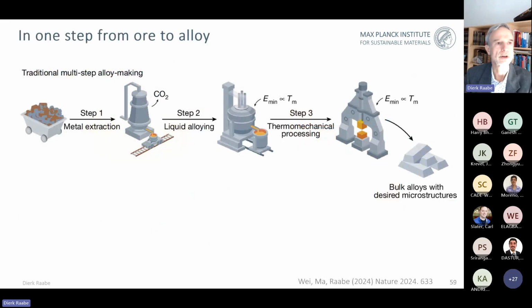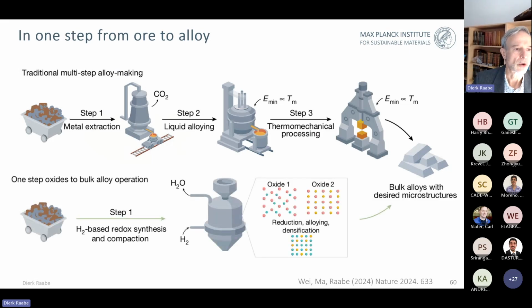And the last example I want to share is what we call one-step metallurgy, from ore or from oxides to alloy. That goes back to our textbook understanding that we have the 3 main steps in our field of metal extraction, the usually liquid alloying to make the actual alloys out of the different metals that we extracted, and then subjecting everything to thermomechanical processing to really leverage the cosmos of our microstructure features to arrive at the desired bulk alloys with their specific microstructure and properties.